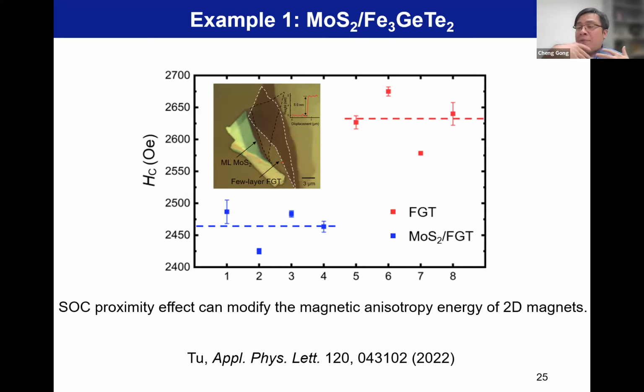Of course, when spin orbit coupling is involved, it's not so precise to simply use the orbital concept. But many times in calculations, when they try to analyze whether out-of-plane or in-plane anisotropy is enhanced, we still use the orbital language. Because of the orbital magnetic moment difference, spin orbit coupling has an orbital dependence, and then they will cause enhanced out-of-plane or in-plane anisotropy. So tungsten certainly has stronger SOC, but whether it enhances in-plane or out-of-plane anisotropy more is case by case. I don't think we can easily give a conclusion, but certainly there will be some strong effect. Yeah, that's my view.